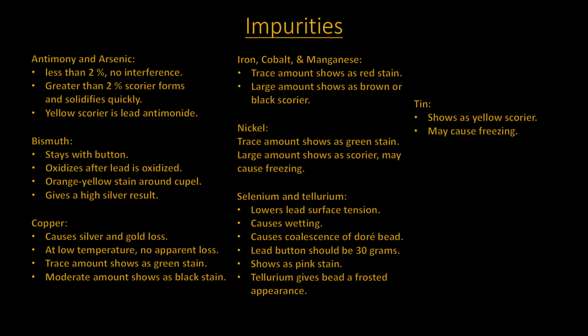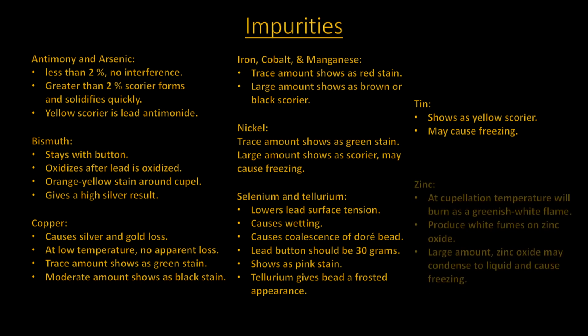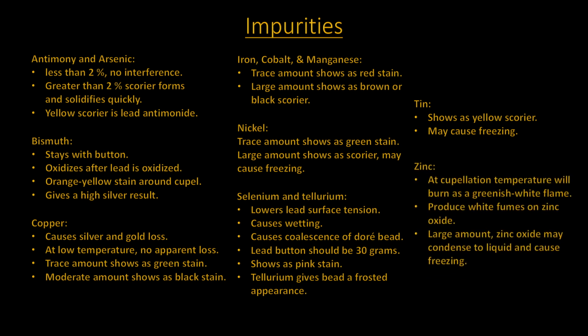Tin shows up as a yellow scoria, as during oxidation to tin oxide. If there is enough tin in the bead, it will choke it off from the atmosphere, causing it to freeze. Zinc, on the other hand, will burn as a greenish-white flame, forming dense white fumes of zinc oxide. This may condense on the cupel if the quantity is large enough and fully cover the bead, causing freezing of the bead.